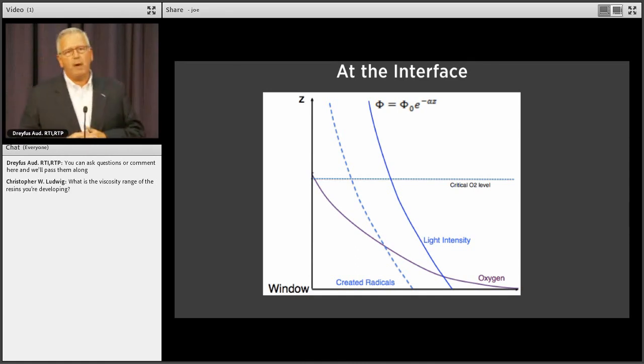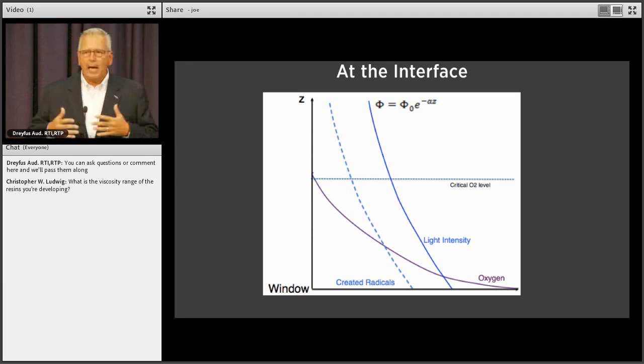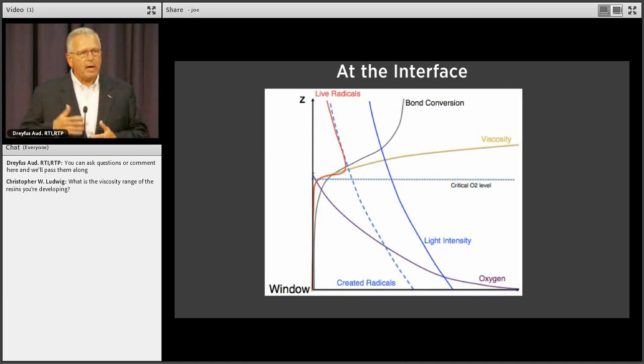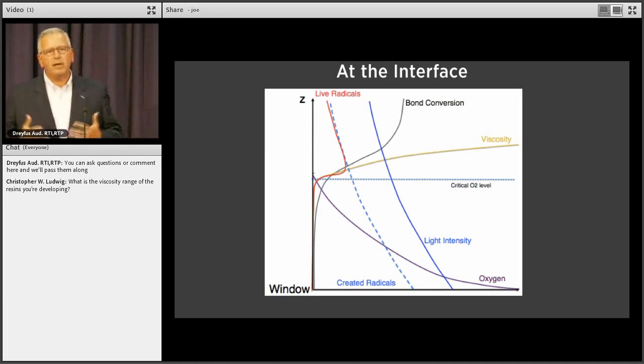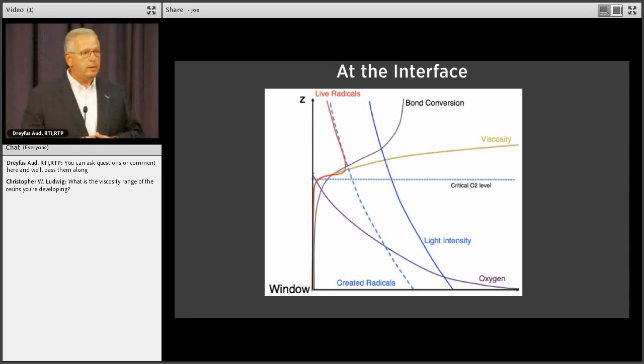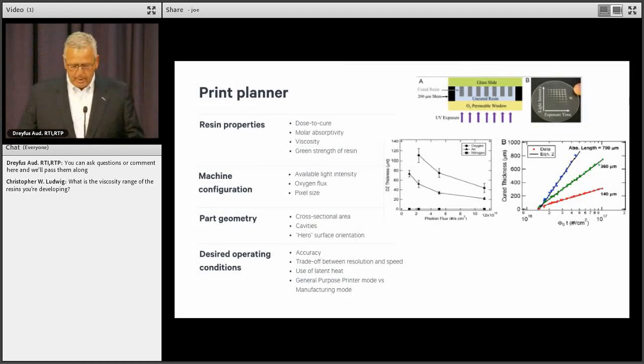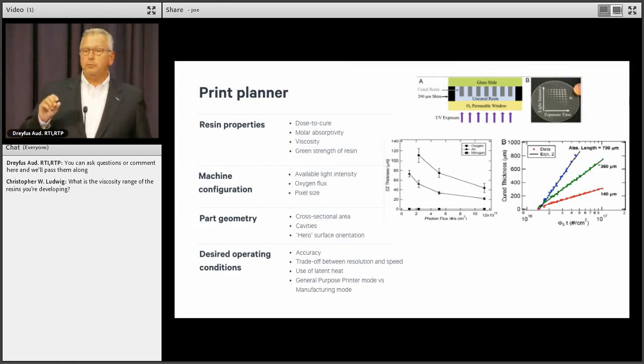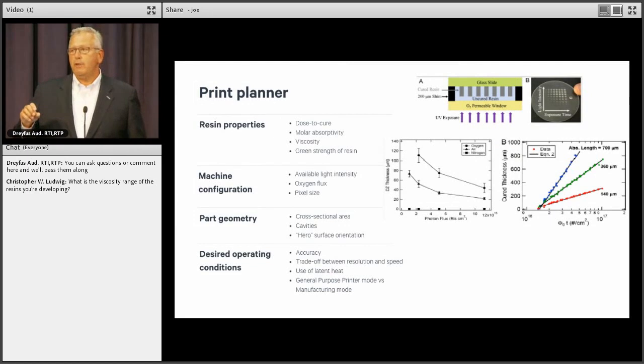And those radicals consume oxygen. This happens in all free radical polymerizations. Once the oxygen concentration gets below a certain threshold, then the polymerization takes off, and viscosity goes through the roof, and we start converting the resin to polymer, and we get bond conversion. And so we're really controlling that gap by controlling a set of chemical reactions, light intensity, and oxygen flux, and there's a whole bunch of things that we have to control in order to control the dead zone, especially in a printer that is a general purpose printer getting an arbitrary geometry every time somebody hits the print button.